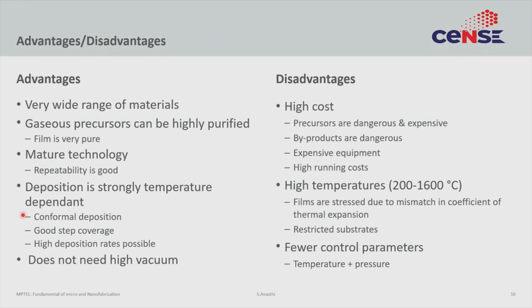So, CVD is one technique where we are around millitorr, maybe higher than millitorr, in the torr or a few torr range. That is not a very low pressure, and it can easily be achieved by typical rotary pumps. So, that is an advantage.